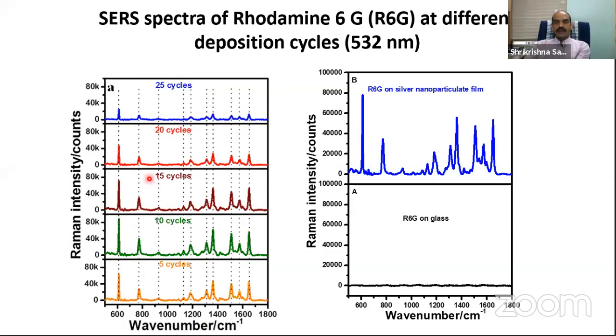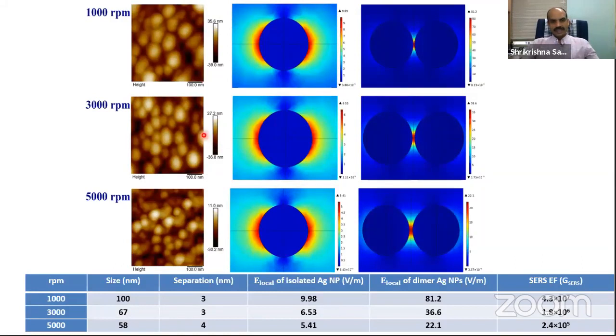What does it mean? The localized surface plasmon resonance peak should be close to the incident wavelength. Otherwise, I will not get the most intense Raman enhancement in the Raman peak. So I can get the most intense SERS spectrum for 25 cycles, and I have already shown you that it is becoming now about 80,000. So this is how we understand and optimize the silver nanoparticles, which will give me a more intense Raman signal.